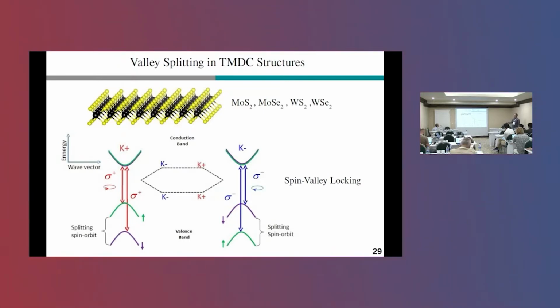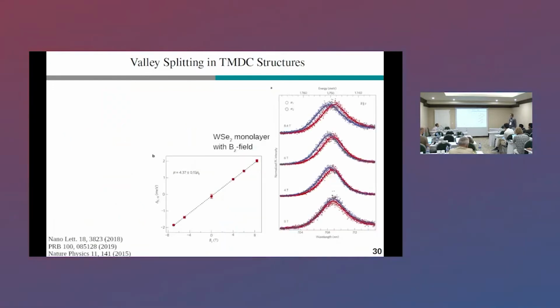The important thing is, if you do optical measurements, then the plus K valley will react to the sigma plus polarization, and the minus K valley to a sigma minus light polarization. So if you do photoluminescence experiments at zero external magnetic field, you will find that the PL peaks of the two polarizations coincide, right? Because they are energetically degenerate.